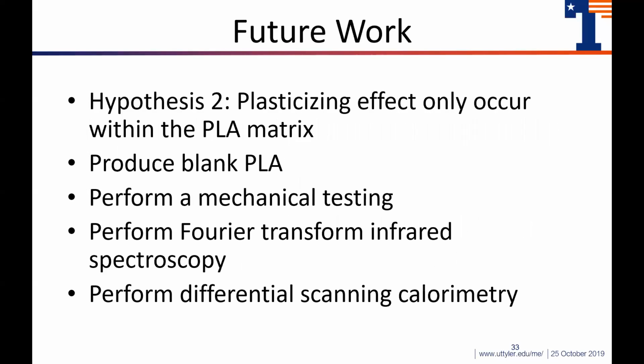So if hypothesis 2 is occurring, we believe that the plasticizing effect is only really occurring within the PLA matrix itself. To test this hypothesis, we'll produce a blank PLA sample. We'll then perform the decontamination times of 1, 3, and 5 hours, and then we'll perform mechanical testing on this. If we're able to see a decrease in the stiffness after decontamination, we know that there's something happening with the intermolecular bonds. And then we'll also perform Fourier transform infrared spectroscopy, or FTIR. This will allow us to see if there's any change of the peaks, which means that the bonds within the molecule are being changed.